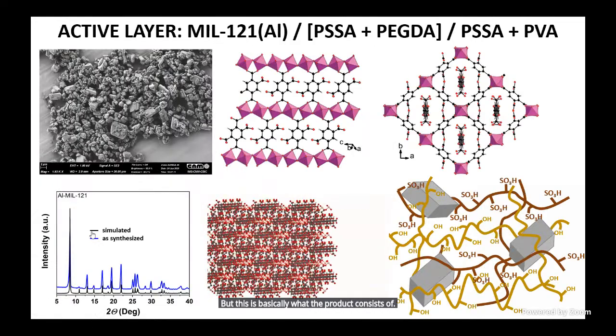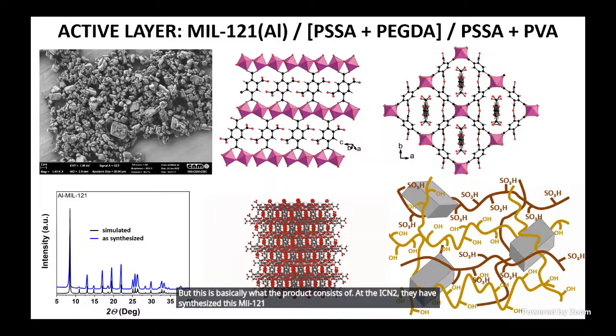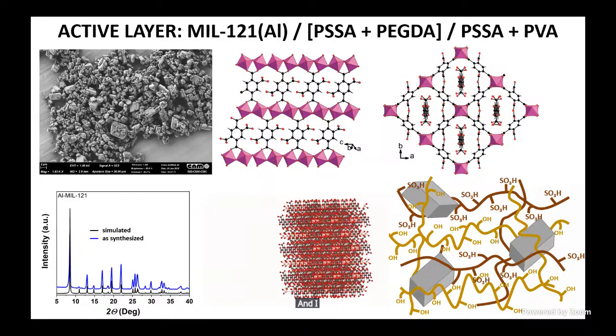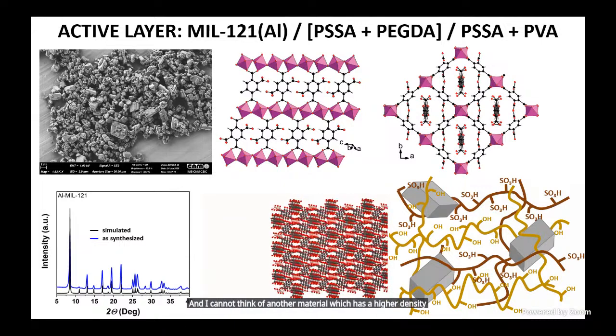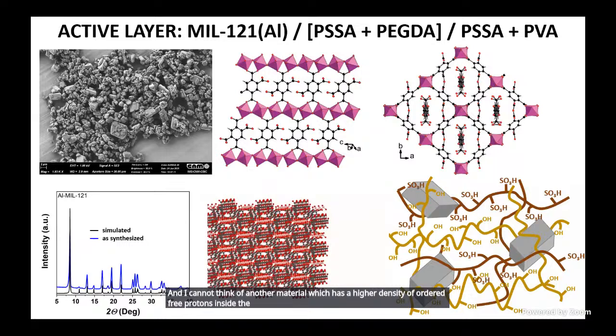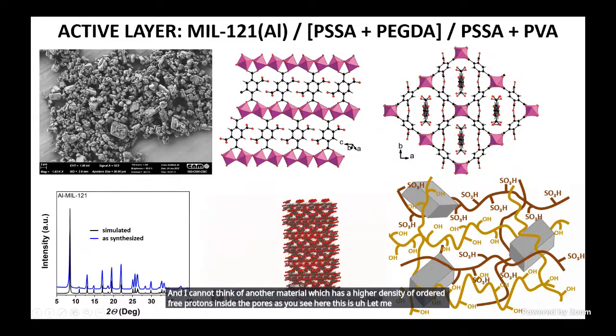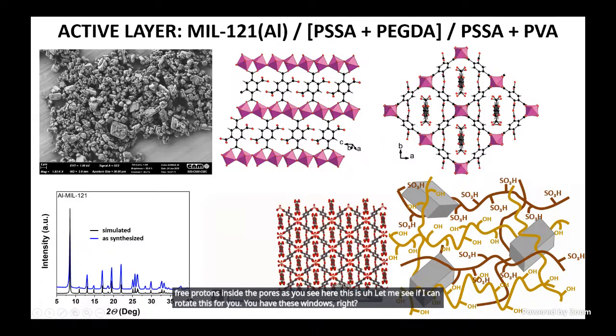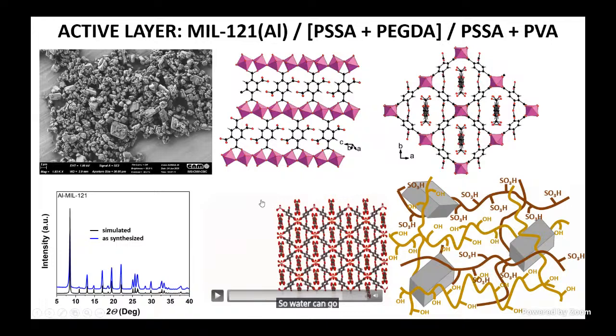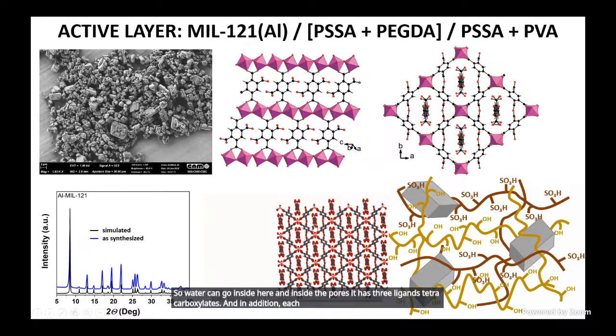At the ICN2, they have synthesized this MIL-121 aluminum, which has this crystalline structure. And I cannot think of another material which has a higher density of ordered free protons inside the pores, as you see here. Let me see if I can rotate this for you. You have these windows, right? So water can go inside here, and inside the pores, it has free ligands, which are tetracarboxylates. Inside the pores, it has 4 free carboxylates, and in addition, the ligands forming the structure also have 2 free carboxylates. So this density of carboxylate groups seems to be ideal for this kind of application.